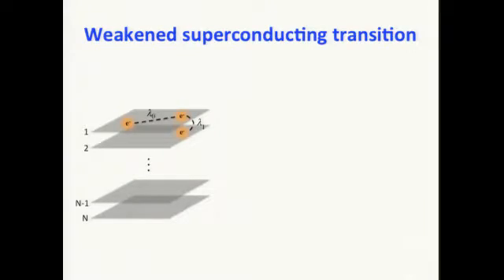But for the decreased TC, we can actually understand the origin of the decreased TC quite well using this simple model. In a layered superconductor, there are two channels that the Cooper pairs can pair, the electrons can pair up. The first is the intralayer channel, represented by this lambda 0 here, intralayer pairing channel, and the other is the interlayer pairing channel, lambda 1 here. So when you reduce the thickness of the material, say in the monolayer limit, the lambda 1 is gone, so you basically decrease the effective coupling to form the Cooper pairs.